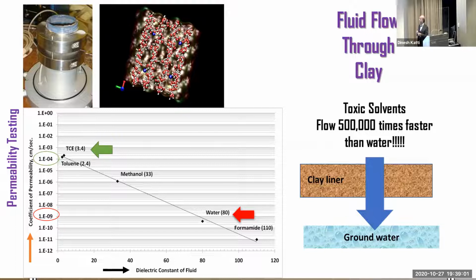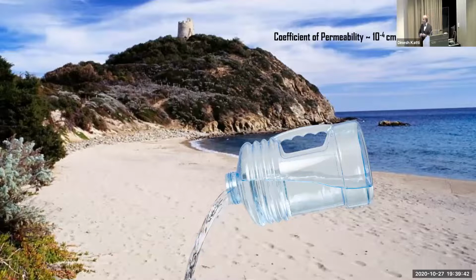On the other hand, when you look at toxic solvents like TCE and toluene, actually EPA has called both TCE and toluene among the top 10 most toxic substances found in our landfills. When you look at TCE and toluene, that number jumps up from 10 to the power minus 9 to 10 raised to the power minus 4. It's a huge jump. In fact, if you look on the right, toxic solvents flow 500,000 times faster than water through this clay liner. That's huge.